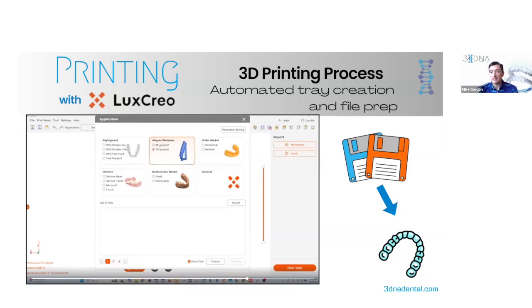That's an interesting prospect, and I was always really intrigued by it. But there are some negatives that we found, which is the post-processing workflow that comes with that type of aligner. You cure in nitrogen and you don't clean that product off with isopropyl alcohol to remove any residual monomers on the outer layer. That was pretty scary for us, and it was a new concept. So we didn't always have the best experience with that, and that kind of pushed us away. And then the material itself is very different from traditional aligners, which is a little bit less clinically proven or friendly to the clinic since it's such a transition.